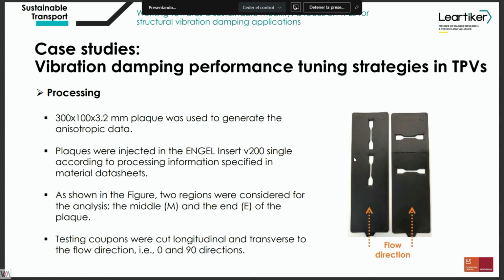And as you can see in the figure, we consider 2 regions. So we consider the middle of the plate and also the end of the plate in order to also analyze the effect of the flow when going through the mold, okay? And then we cut the testing coupons longitudinal and transverse because, as I mentioned, the objective is to analyze the anisotropic behavior of this kind of materials.